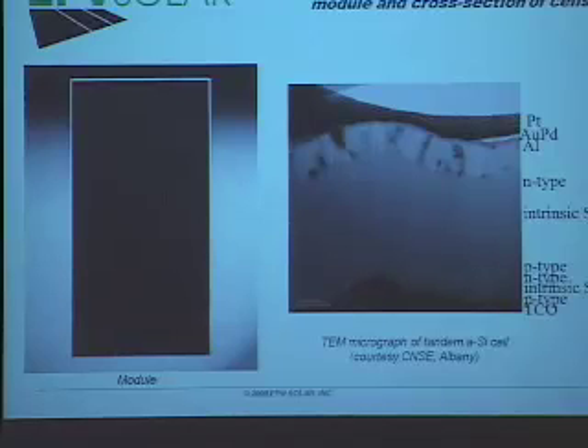The left-hand slide is a picture of the solar cell. You can see the vertical stripes. Each of those long stripes is one solar cell akin to the crystalline wafer in the conventional panel. And on the right, you see the cross-sectional structure of the actual device. So we go to the larger area. Looking through the thickness of the device, you can see at the bottom the transparent conducting oxide. It's not a planar surface, it's deliberately textured. You can see P, I, and N layers and another set of P, I, and N layers. And controlling these morphologies and layers is of extreme interest to us.